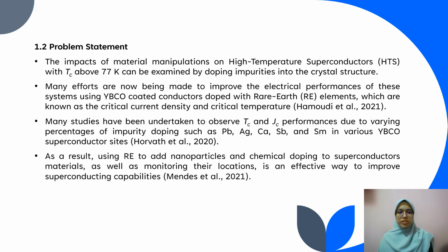Second, problem statement. The impacts of material manipulation on high temperature superconductors with Tc above 77 Kelvin can be examined by doping impurities into the crystal structure. Many efforts are now being made to improve the electrical performances of this system using YBCO coated conductors doped with rare earth elements, which are known for the critical current density and critical temperature.